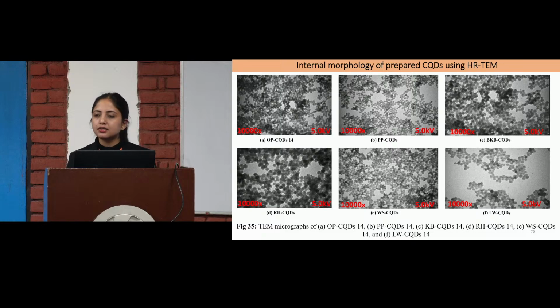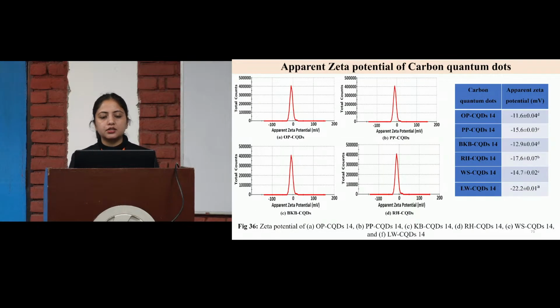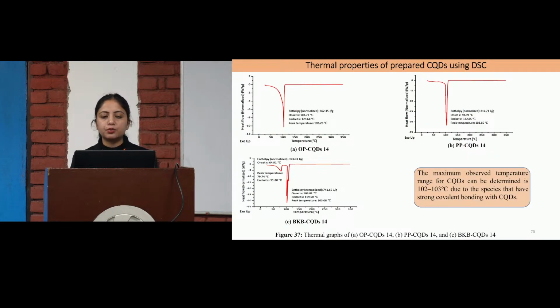Then we checked the internal morphology of the carbon quantum dots, as they have a spherical structure. You can see in the figures there is a spherical structure, but there is no agglomeration in the carbon quantum dot synthesis, so they have higher stability. After that, the apparent zeta potential of the carbon quantum dots: a higher zeta potential means there is a charge. To check the charge of the molecules present in the carbon quantum dots, they have zeta potentials of minus 11.6, minus 15.6, minus 12.9, minus 17.6. These are the apparent zeta potentials of the carbon quantum dots.